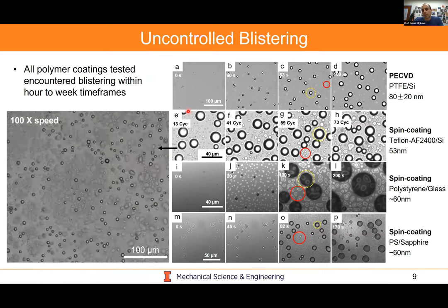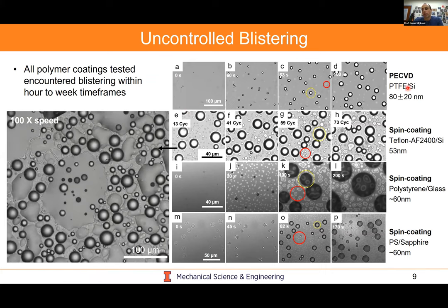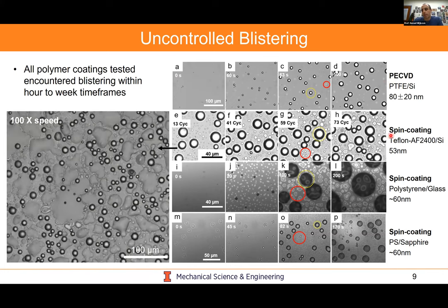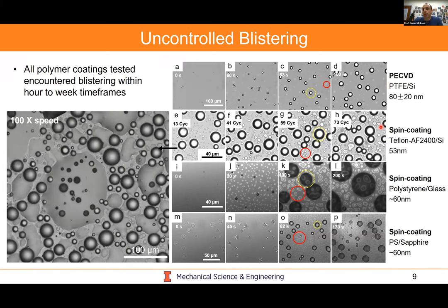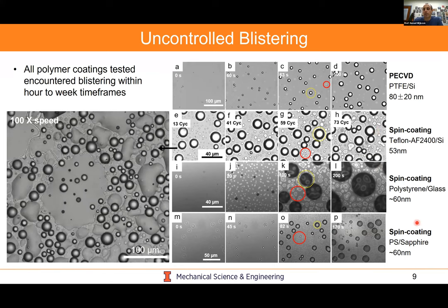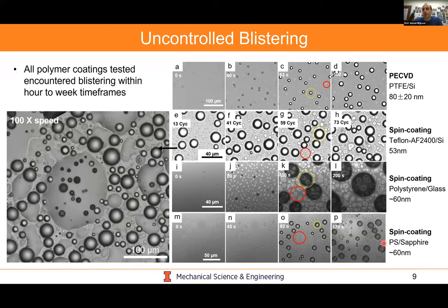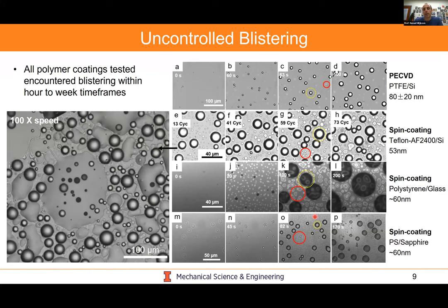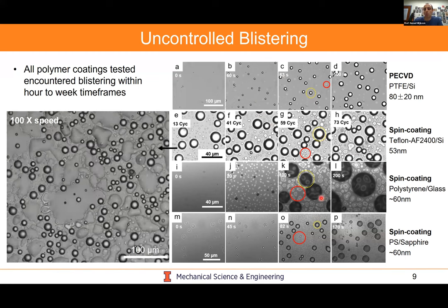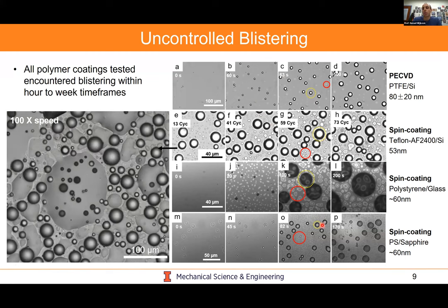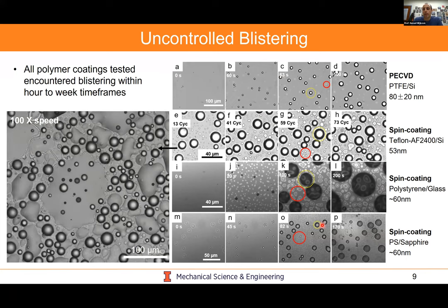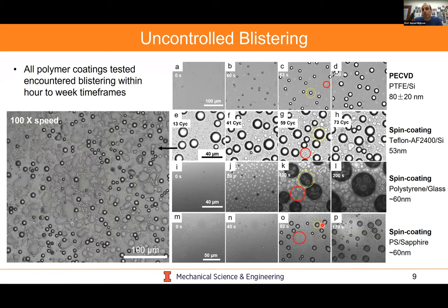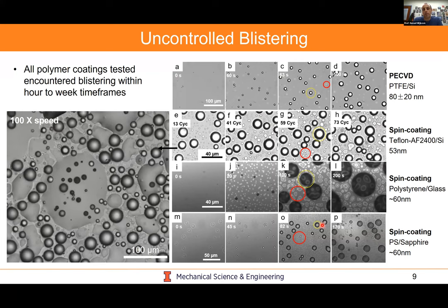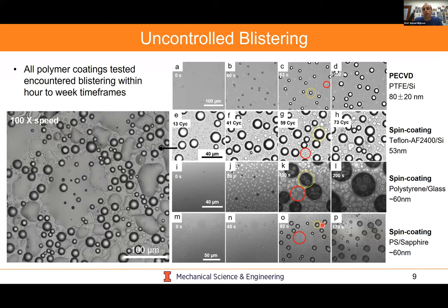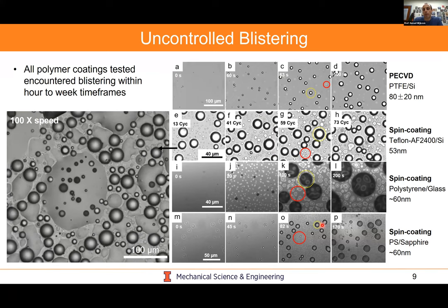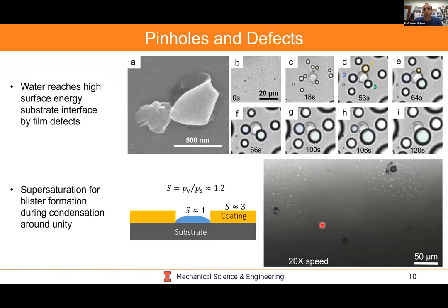We looked at a multitude of different surfaces, like PECVD of a Teflon-like substance on silicon. We looked at different manufacturing techniques: spin coating of Teflon AF, polystyrene on glass, as well as polystyrene on sapphire to vary the adhesion properties of the substrate. And everything we did showed us very qualitative results, nothing very quantitative. This made us take a step back and think about what's happening and how we can develop materials rigorously, understand them really well, and then develop clean experiments to understand why these blisters are forming and how we could prevent them.